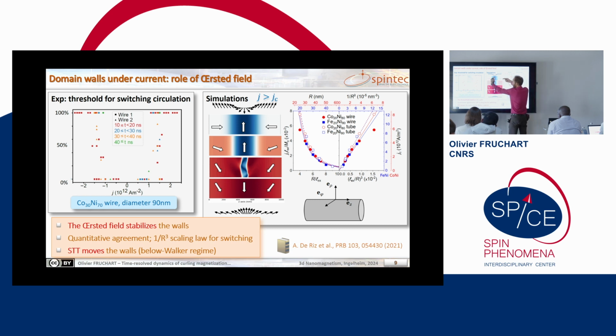This is longitudinal magnetization. It is unrolled, and this is the peripheral magnetization. And so you can switch from positive or negative to positive. And we predict with analytics that this threshold current should vary like 1 over the radius cube. And the physics is very simple. The cost in exchange of curling varies like 1 over r squared.